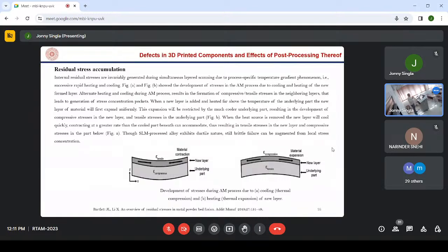Internal residual stresses are invariably generated during simultaneous layered scanning due to process-specific temperature gradient phenomena. Whenever you are adding material layer by layer, a temperature gradient is always introduced, and that temperature gradient is responsible for residual stress accumulation. Successive rapid heating and cooling: figures A and B show the development of stresses in the AM process due to cooling and heating of the newly formed layer. Alternate heating and cooling during the AM process result in the formation of compressive and tensile stresses in the neighboring layers that lead to the generation of stress concentration pockets.